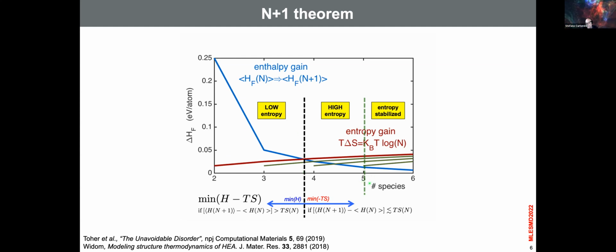Then on the other side, when you increase the number of species, you have a region which is entropy stabilized, where you have as much entropy as possible, and you see that entropy really rules, no matter if some of these sublattices are ordered. So pretty much here you don't care anymore about enthalpy, and everything you need to care about is entropy. And then there is another region in between where there is a little bit of entropy, a little bit of enthalpy. So you need to pretty much balance them together and see who wins.